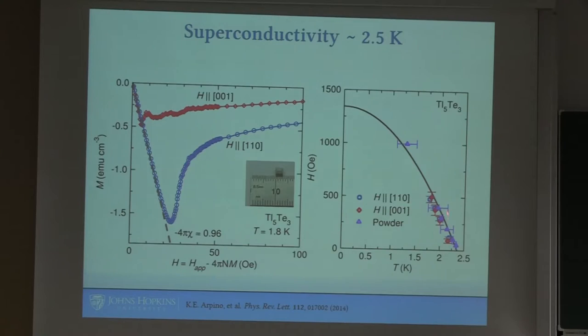And this has disturbed us for a long time, and I still can't fully explain it, so if you have an idea, please talk to me about it. But here's essentially the problem. The HC2s are basically the same, independent of crystal direction, and they match the powder very well. On the other hand, if you look at the low magnetization data, you would say that where it starts to deviate from perfect Meissner shielding varies between the two crystal directions. And I have a problem with that, because there's something called the thermodynamic critical field in a superconductor, which is essentially the geometric average of HC1 and HC2. And in a tetragonal material like this, the HC1 and HC2 can vary with crystal direction, but their geometric average needs to stay the same, because it needs to be able to match what you see in a bulk-specific heat measurement. And that's not the case here, and I don't have a good explanation for that. Things like demagnetization and all the usual sort of extrinsic sources, we checked - we made little spheres of this and this kind of thing.